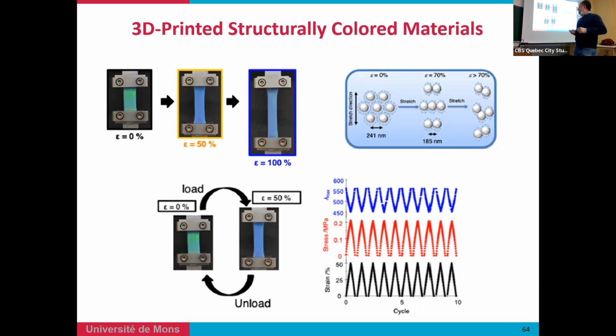We carry out a tensile test, from 0% deformation to 50%, and you can see that you pass from green to blue to more dark blue using that. But it's reversible, so it means that you can stop stretching the sample and you recover the green color that you have initially from the system.